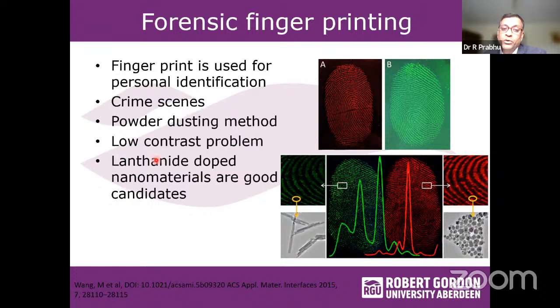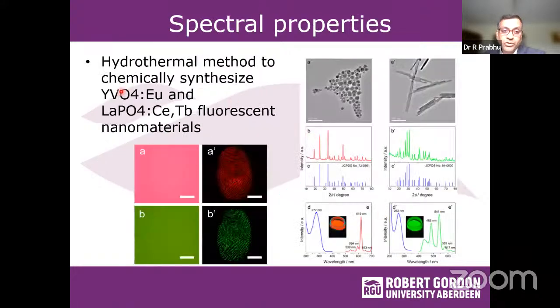And this group was trying to develop lanthanide doped nanomaterials for using as test material. So you can see they developed Eu-based and Tb-based nanomaterials, and that can enhance the quality of the detection or fingerprinting. So they used these 2 Eu and Ce-Tb-based combinations, one in green and one in red. Eu is in red and Tb, this one in green. So under white light or a normal full bright condition, this is the typical image. So you can see the contrast is very bad.